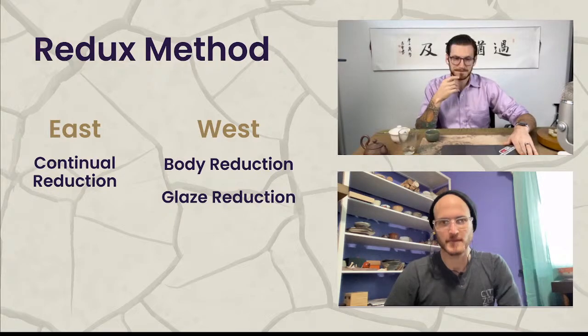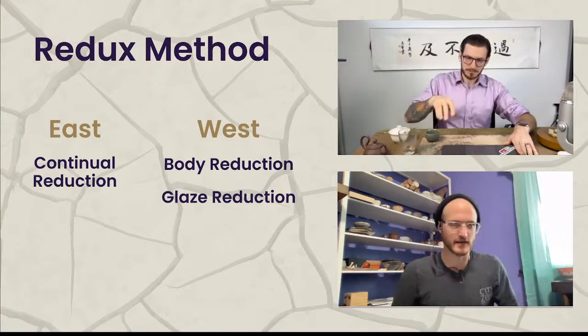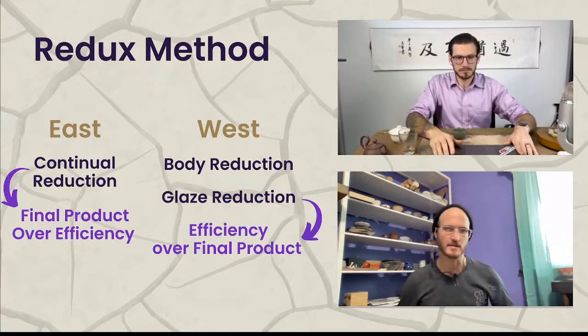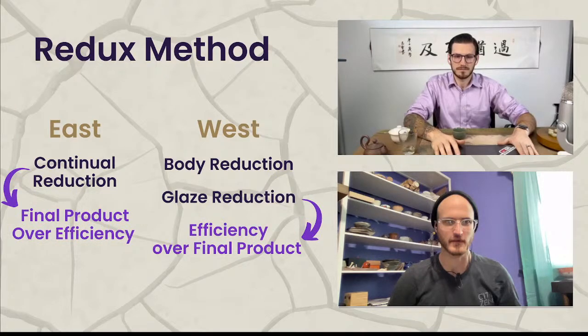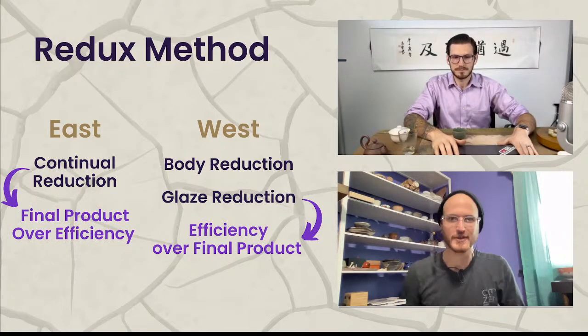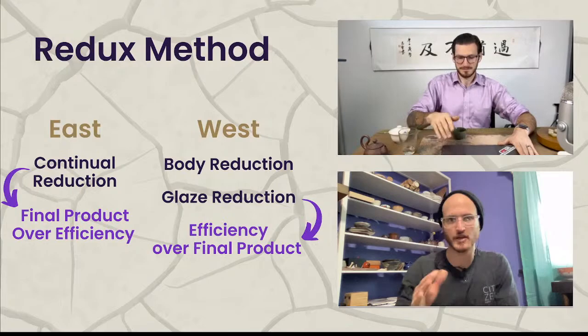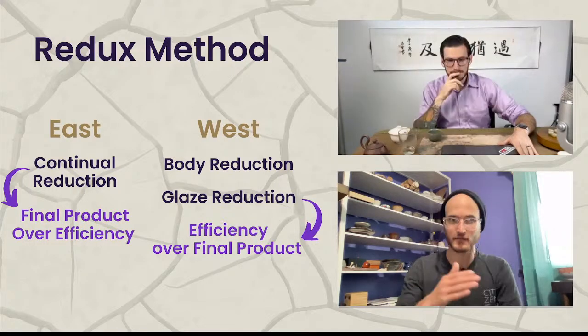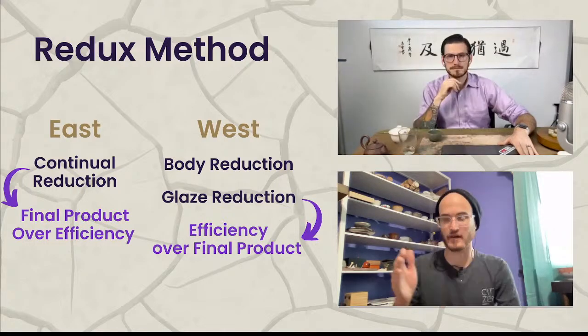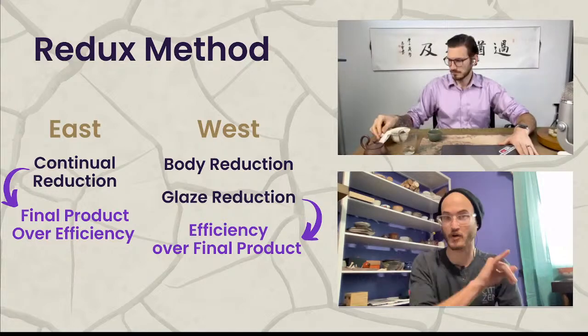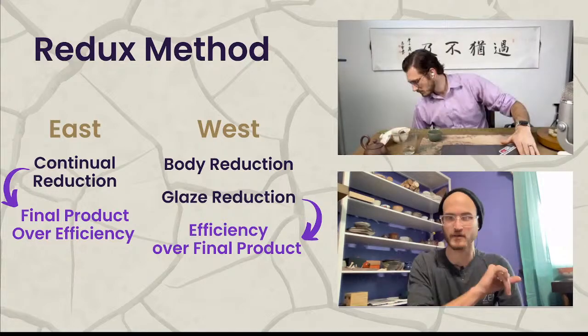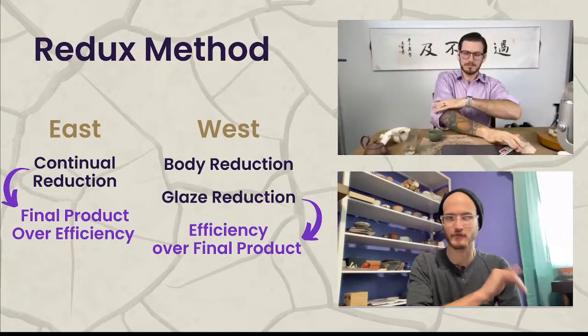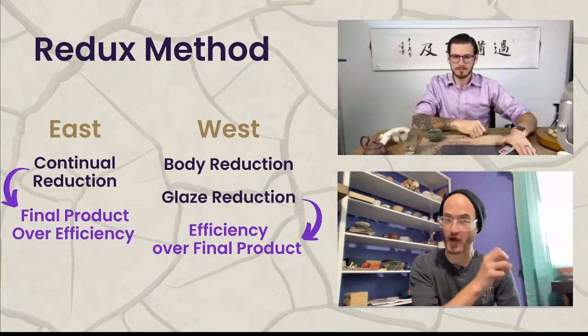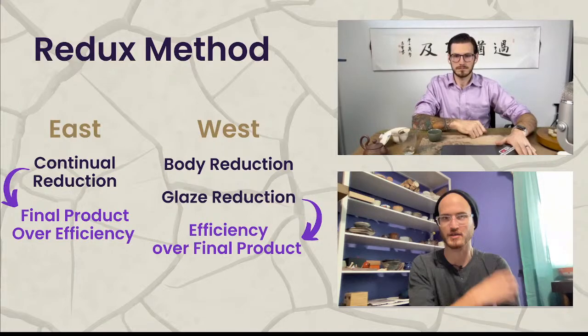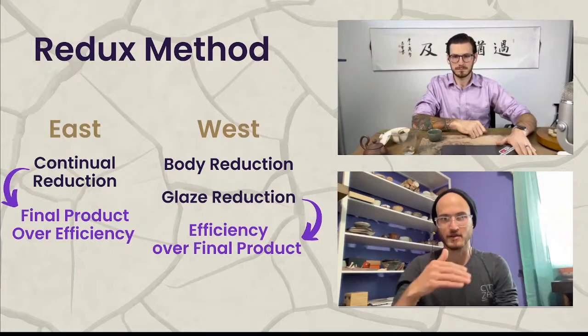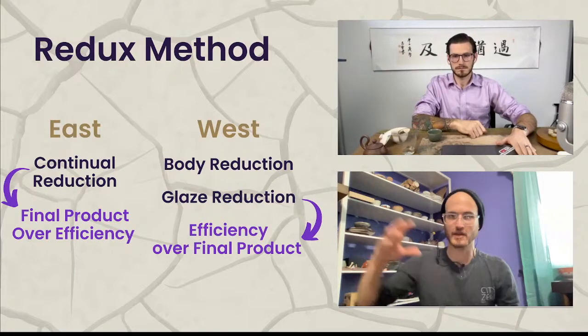Yeah, and I think we have a slide for that, but it's basically the difference in philosophy, right? You're really focusing the kiln on what your result will be. So I do a mild or medium reduction throughout the entire firing. I also do a heavier reduction when I first start after 900 C in order to sort of lock in that body reduction, and then I do a crash reduction, but I do a reduction throughout the whole firing because I want to develop the surface.